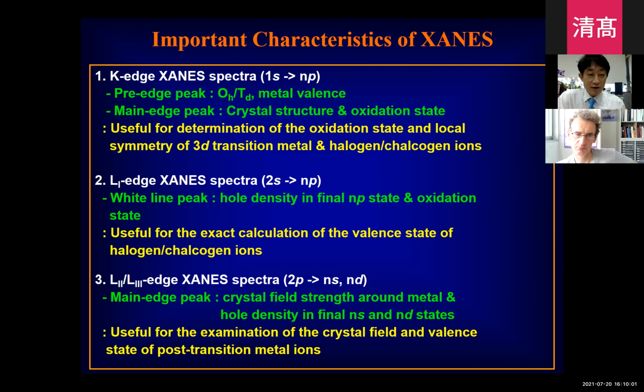In the case of the L1-edge, we can see the transition from 2s to unoccupied np. This transition normally gives a very strong white line peak. So from the intensity of the white line peak, we can precisely determine the hole density in the final np state. It is very useful to determine the valence state of halogens or chalcogens because they have unoccupied states in the np state.